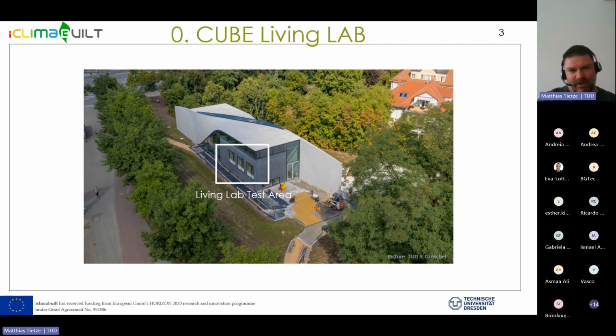It has two very interesting parts. One of them are the twist elements. These are very light concrete shells. They are curved and they are a wall and a roof and all in between. So we could show what we could do with carbon reinforced concrete now. And we also built a box. This is the black thing where the white square is around. This is a prefabricated part in carbon reinforced concrete. In this box, there are three rooms integrated, where we could implement our test cases.